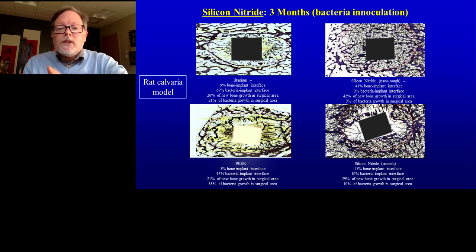But still, we saw 10% of the surface of the smooth silicon nitride covered with bacteria. So 10% is still a pretty large amount. In fact, you can see there's gaps in bone growth surrounding that implant. So those gaps in purple color, the white color, are regions of no bone growth. And that's because there was bacteria that was present in those locations. So there's still reason for improvement for that smooth silicon nitride.